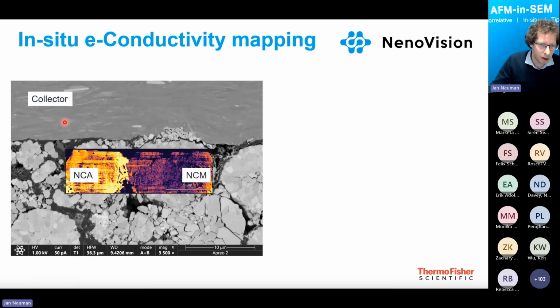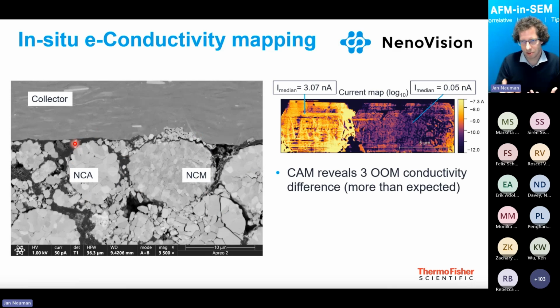This is exactly performed on this area. So straightforwardly, you see a big difference in the conductivity of the particles, much more than expected. What we see on the NCA is about 3 nanoamps. On NCM, it's 0.05 nanoamps, so 3 orders of magnitude difference, which is more than expected.